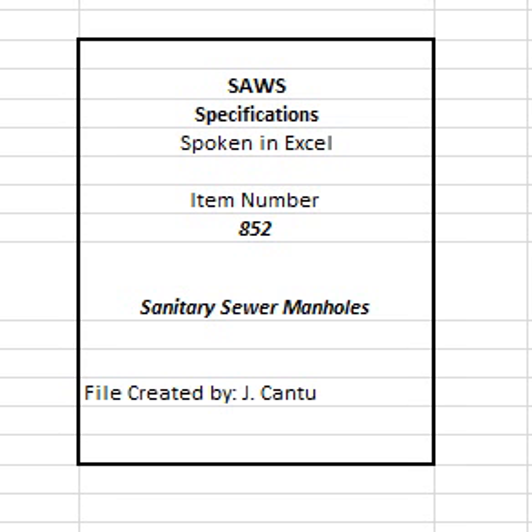8. A vacuum of 10 inches of mercury shall be drawn, and the vacuum pump will be turned off. 9. With the valve closed, the level vacuum shall be read after the required test time. 10. If the drop in the level is less than 1 inch of mercury, final vacuum greater than 9 inches of mercury, the manhole will have passed the vacuum test. 11. The required test time is 2 minutes.